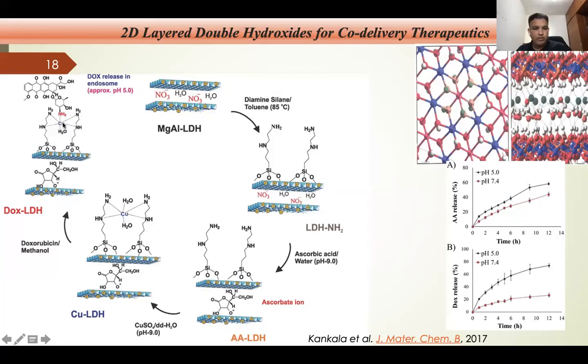Even by using this copper chemistry, with the same coordination bond breakage, we could also achieve the delivery of doxorubicin specifically in the acidic pH, that is the cancer pH. And even ascorbic acid could be released as much as possible in acidic pH. The reason behind this is these layers were a bit sensitive to acidic environment. So we don't really need any sort of bond-breaking things, because this material is sensitive to acid. So in acidic pH, these could be broken down.